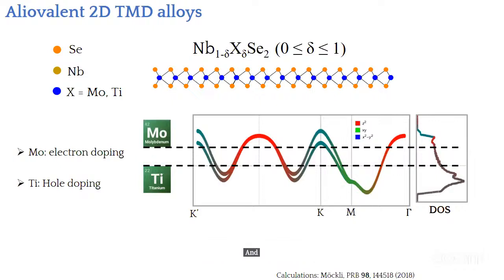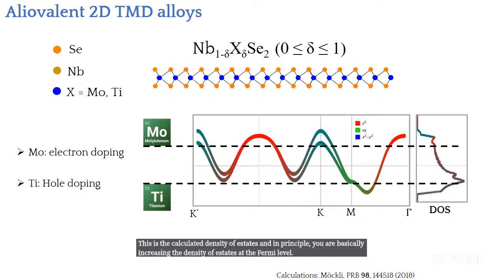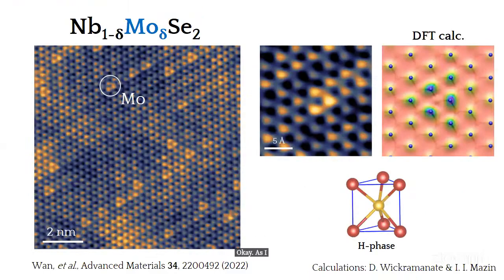And this is the expected effect of the molybdenum. If you go to the molybdenum, as you add more and more molybdenum, basically you electron dope it. And in this case, in principle, the density of states decreases. If you dope it with titanium, the effect is basically the opposite, because this is the calculated density of states, and in principle, you are increasing the density of states at the Fermi level. Okay. As I said, I will only mention the molybdenum case. So here I show you an STM image of a very dilute concentration of molybdenum atoms that can be recognized easily.